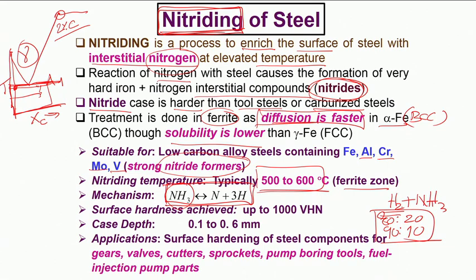More hydrogen is used because it creates conditions whereby surface oxides get reduced easily and nitrogen can move in. There is also a school of thought that hydrogen helps create a thin plasma which removes scale or oxides. The process achieves extremely high hardness — typically 950 to 1000 on the Vickers scale, or easily 70 to 75 HRC in Rockwell.